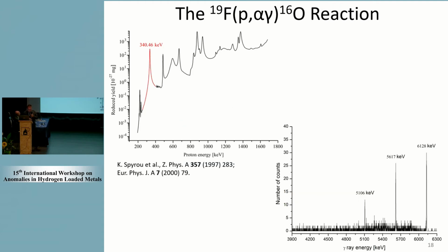Then we studied this nuclear reaction. We set on this resonance. This is protons on fluorine target, and you get an alpha particle, but we measure this oxygen-16 gamma ray, which is here, a very clear spectrum of gamma rays, typical.